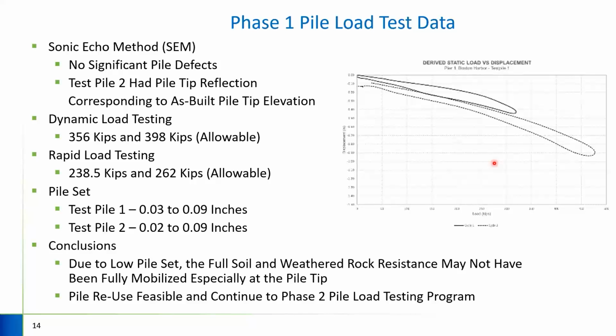Additionally, for the rapid load test, we hit our 240 kips in the second test pile, and we're just slightly under, less than 1% in the first test pile. So these results gave us confidence that we could move forward into phase 2. The pile sets, when we look at those, were less than 0.1 inches, which would indicate that the piles were driven into the soil and weathered rock, and probably did not have their full resistance mobilized, since we did not see significant movement.